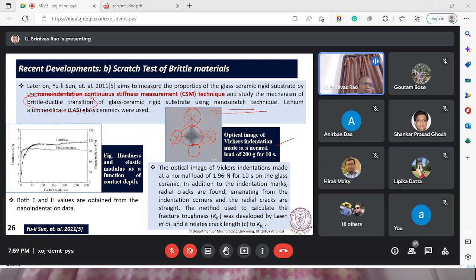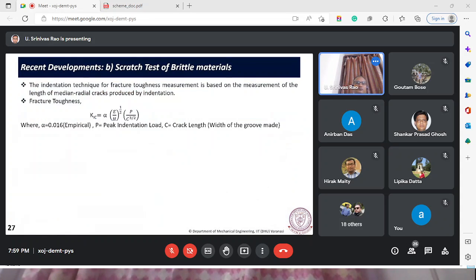So nano indentation is also used, because these are brittle materials. These values are so small that we need to go for very small loads. You can imagine here 1.96 Newton is the load. It's a very small load actually. As I told you, these median cracks are to be avoided. Gradually, when we increase the load, those cracks are obtained. So at different loads, these tests are performed, and from there we get these values.